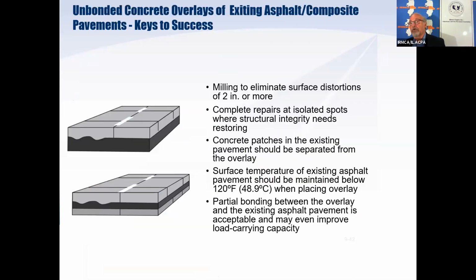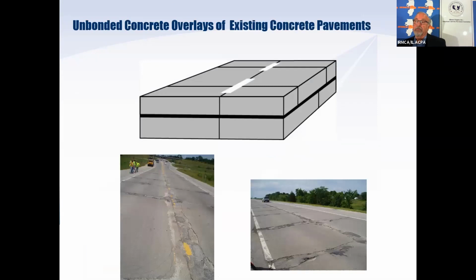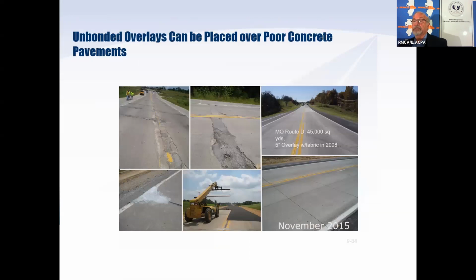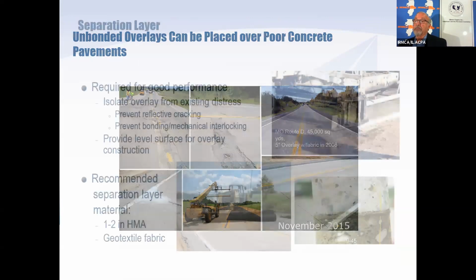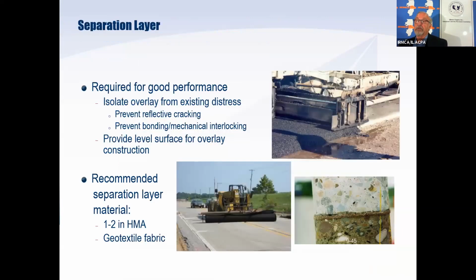And again, a lot of the same criteria apply, such as the 120 degrees. Partial bonding in this case is actually okay. It helps you, it doesn't hinder you. The last overlay we're going to talk about, briefly, is unbonded concrete on concrete. You can put this on a really severely distressed pavement like you see on the lower right. The key is that you're going to separate the old pavement and the new pavement. You can do that by either putting down a thin layer of asphalt, generally less than 2 inches, or a specifically designed geofabric, as you see in the bottom right photo.